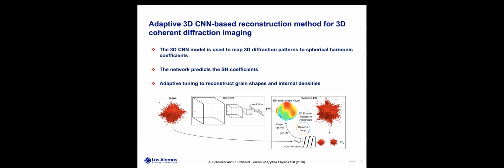So although neural networks offer fast inference, it's important to understand that they are also only approximations, and these approximations can be used as initial guesses to significantly reduce the search space. So for example, in this case, we have used ML for 3D coherent diffraction data analysis. We developed a CNN which takes in these 3D diffraction patterns, and we represent our object, the crystal, as spherical harmonics coefficients. These spherical harmonics coefficients describe the shape of this object and the diffraction pattern.